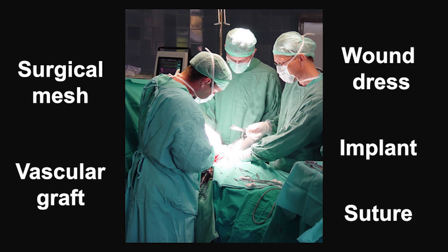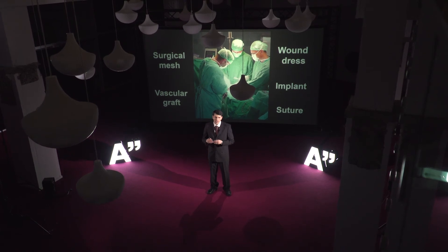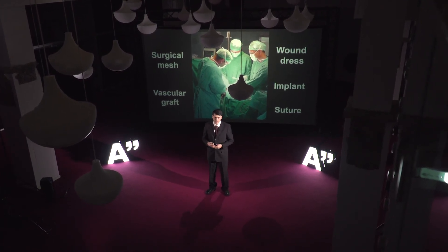Fibers also have many applications in medical textiles. We have worked on two of them: surgical mesh and vascular grafts with very small diameter. Surgeons normally insert a surgical mesh made of synthetic non-resorbable, non-biodegradable polymer — most of the time polypropylene — inside the body for hernia repair and reinforcing the abdominal wall. Sometimes these meshes come into contact with nerves, causing discomfort, pain, and sometimes chronic pain, requiring removal. In one of our projects we produced a resorbable surgical mesh by electrospinning, which after two to three months of strengthening the abdominal wall will resorb in the body — similar to the concept of resorbable sutures.